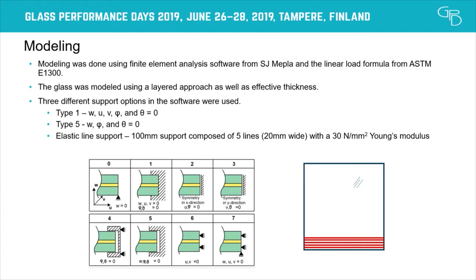The first one I picked is this one right here, which is almost fully clamped, and then number five as well. And speaking with Mepla, they actually recommend using a linear elastic support system, which is basically this one right here. It consisted of 100 millimeters of support at the bottom, made with five lines that were 20 millimeters thick. And the modulus for the elastic material that I used was 30 Newton per square millimeter.